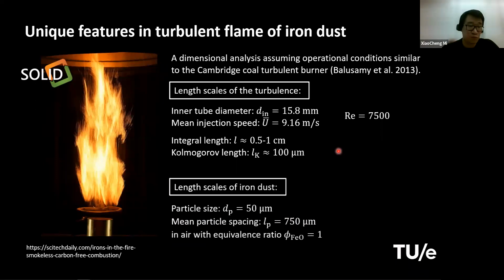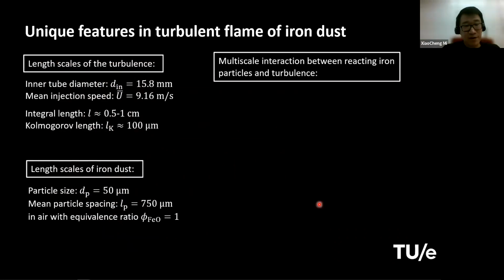But we need to understand how this turbulence interacts with iron particles. So we also need to look into some characteristic length scales of iron dust. Iron particle size in our typical applications would be around 50 microns or on that order of magnitude. And if you are talking about burning them in air with an equivalence ratio of FeO equals 1, then you end up having a mean particle spacing somewhere below 1 millimeter. And if you compare these different length scales of particles and the turbulence, we have a few remarks from this dimensional analysis.